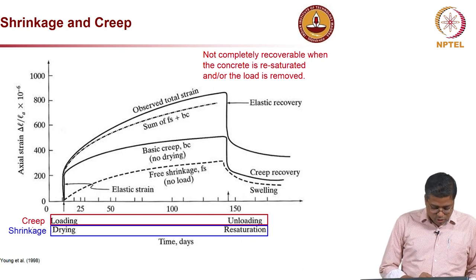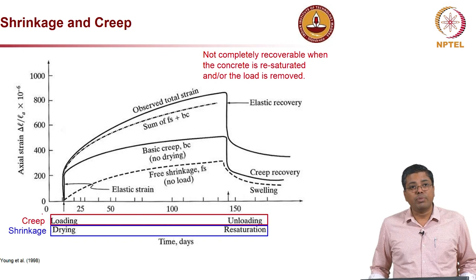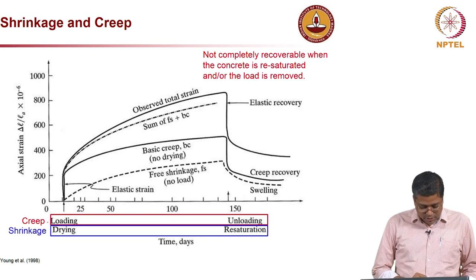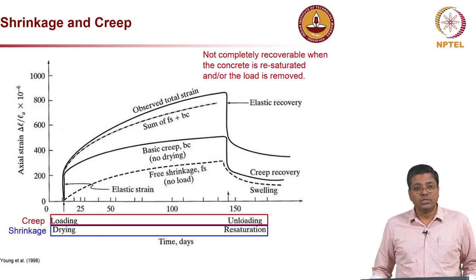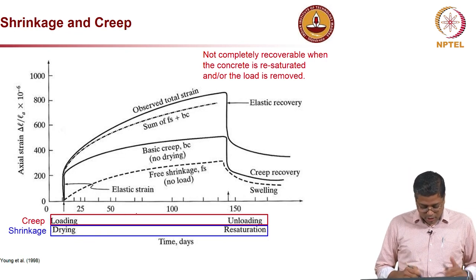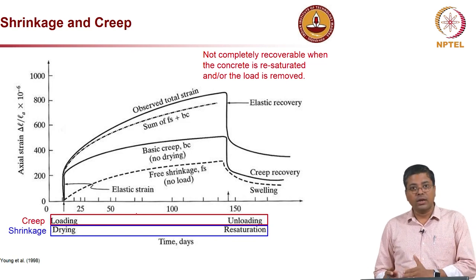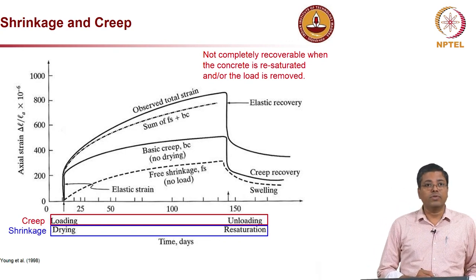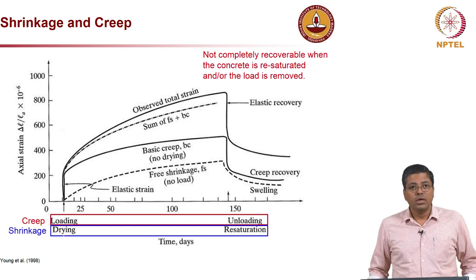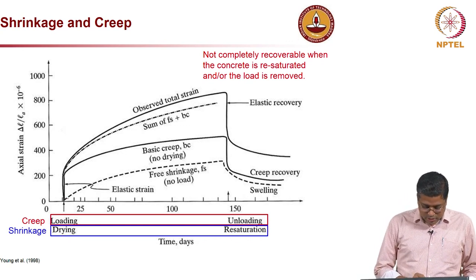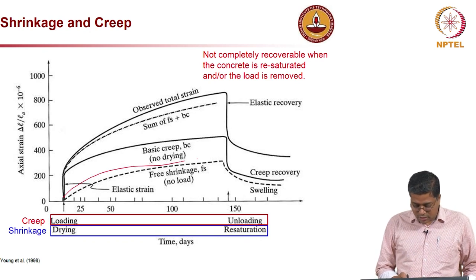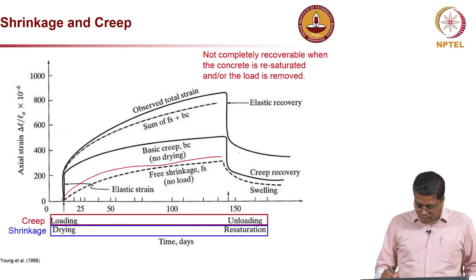This graph here shows both the creep and shrinkage behavior. As you can see, I have put this red box at the bottom, which indicates creep. The reason for creep is loading, and for creep recovery, when we unload, we can see the creep recovery. And in the case of shrinkage, which is the blue box at the bottom, the loading is essentially the drying and the unloading is essentially resaturation. So you can see here the free shrinkage curve, and when the resaturation happens, whatever the strain gain, we are able to recover some of it, but not fully.